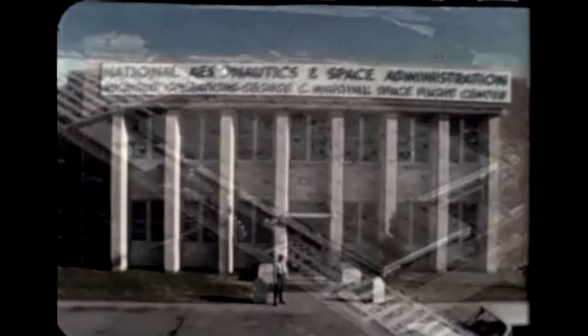In an interim weld facility set up at Michoud, welders were trained to operate the automatic machines used to make the Y-ring welds. Sonic and X-ray testing of welds was conducted to discover any flaws or cracks. The first actual Y-ring weld was performed in Boeing's production weld facility in December, using personnel and equipment formally certified in the interim weld facility. The boring mill at Michoud was put to its initial use in a test operation to machine the first Y-ring segments to finish dimensions. One segment was cut into small sections for test pieces, which will be used for experimental welding to determine if the Y-ring can be welded after it is machined rather than before. Following the tests, the three segments will be welded together to determine the feasibility of welding the completed Y-ring.